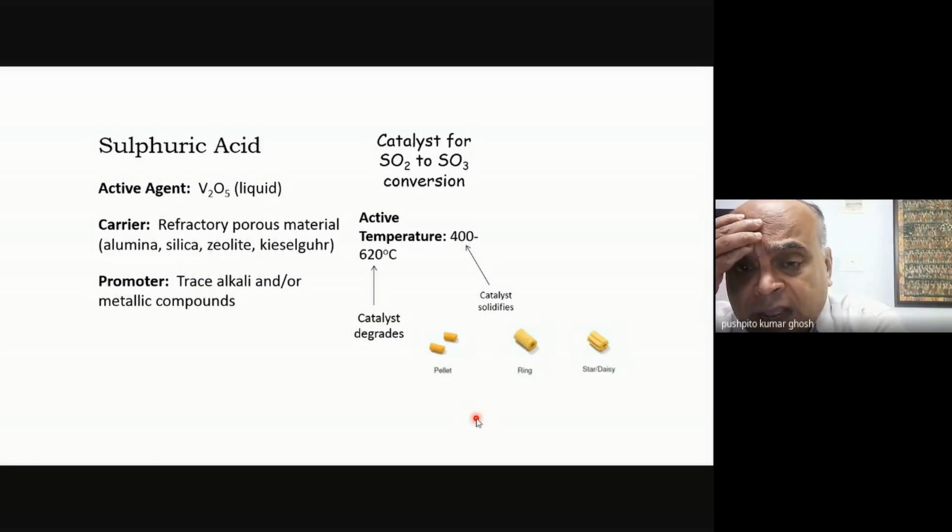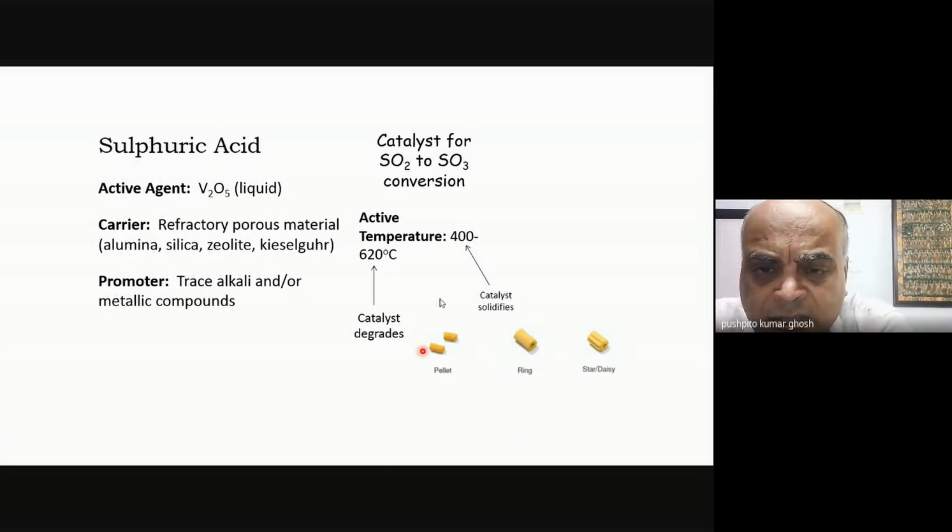And since I have got this problem of conversion falling off very steeply at higher temperatures, I don't think that I would like to exceed a temperature of 600 degrees centigrade in any case. So what they have done is that they have played around in this kind of a temperature range. It's a temperature range, and we'll see the clever stuff that has been done.